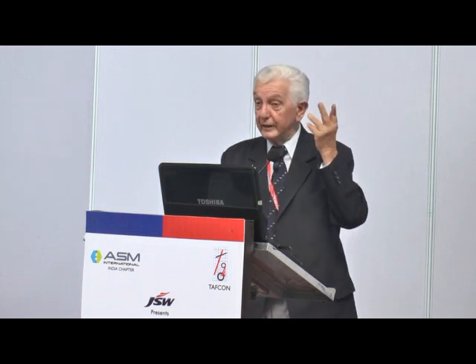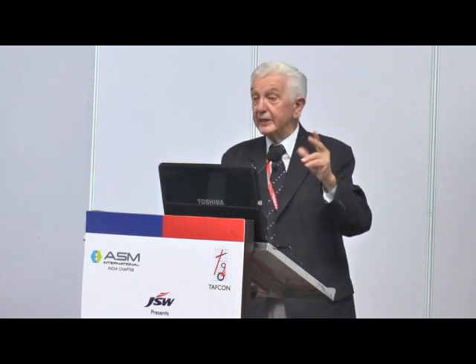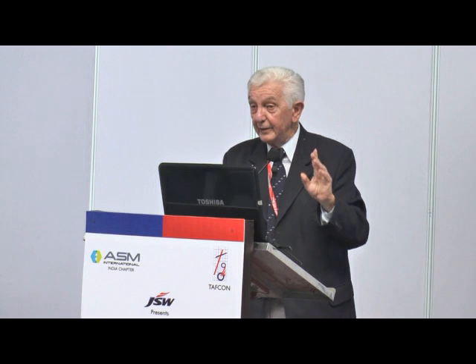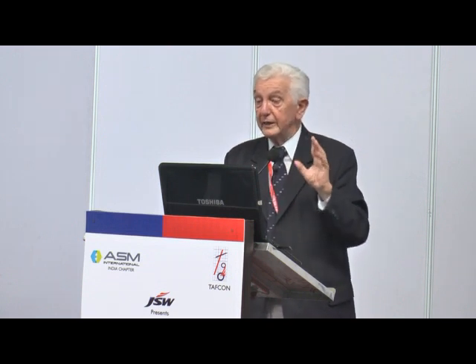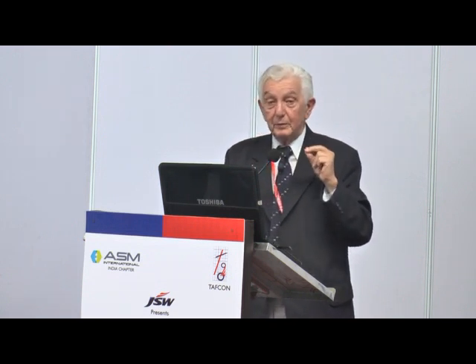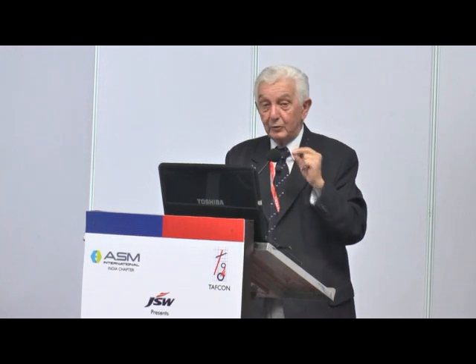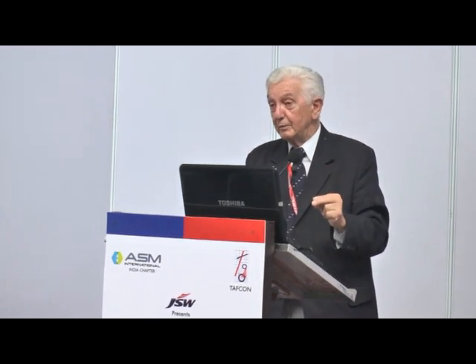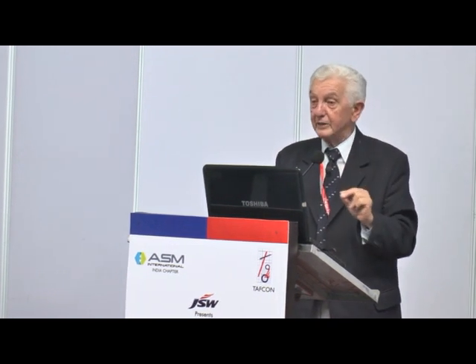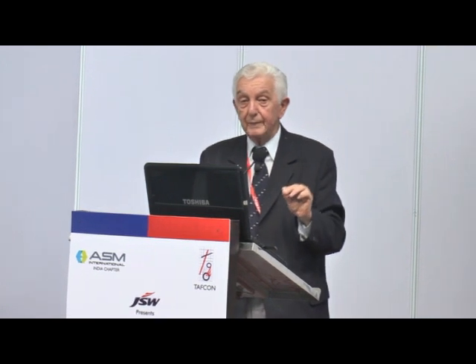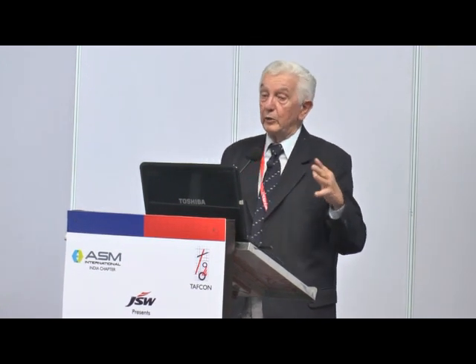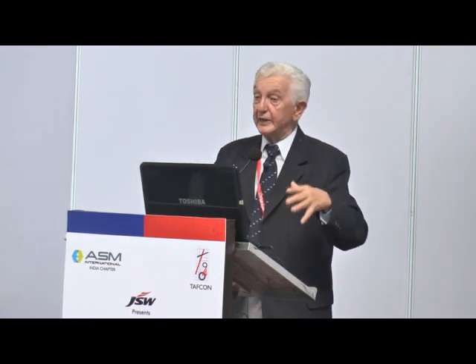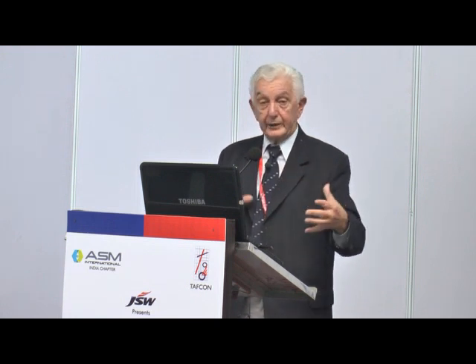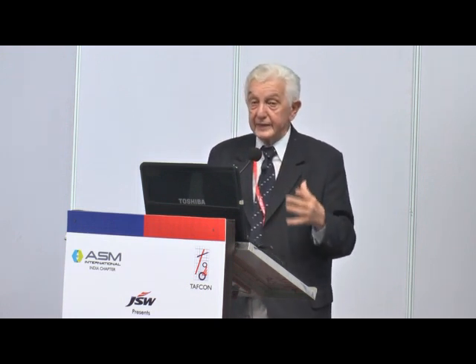Certainly it sounds a little bit strange because it's increasing the energy consumption, that's right. But for small power equipment, what we observed, and I can prove it, is that no edge effect appears and no hollow cathode effect. Why? We do not really know. That's something which we still have to explain, because certainly what we know is that we modify the energy distribution between the cathode and the parts, and this is why.